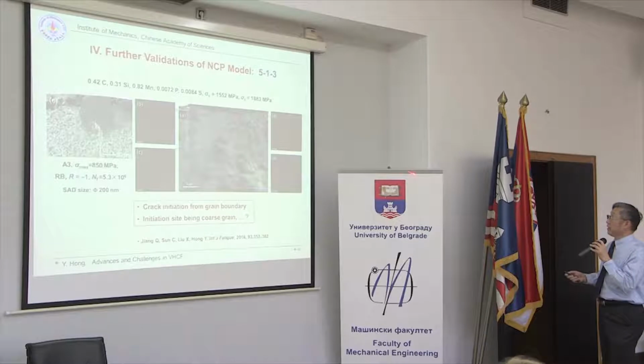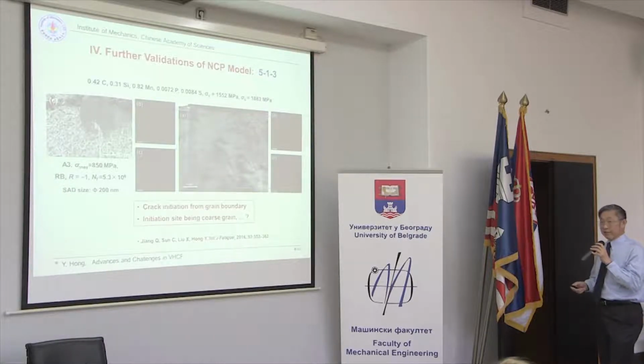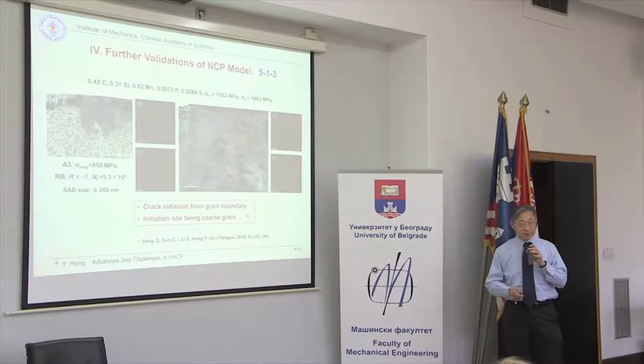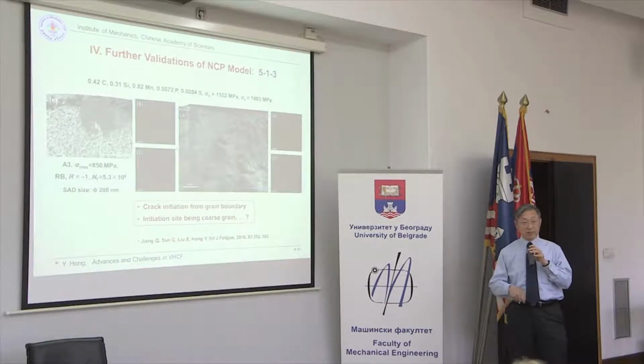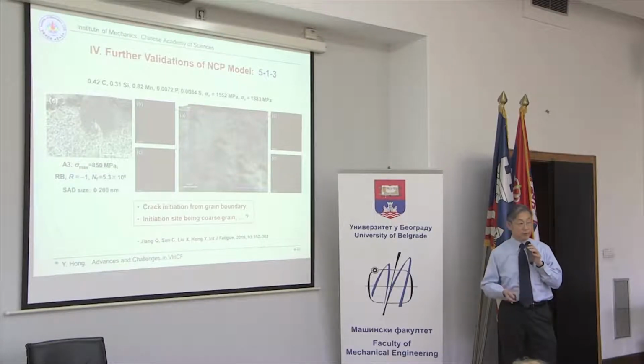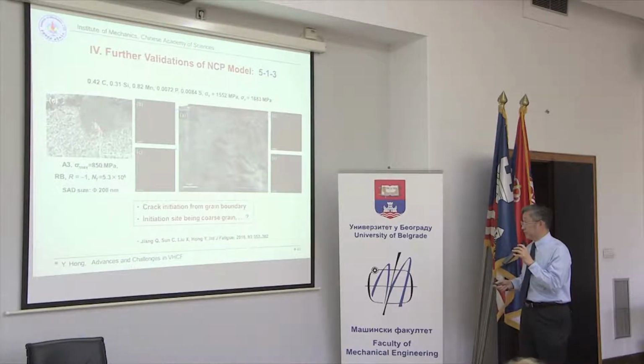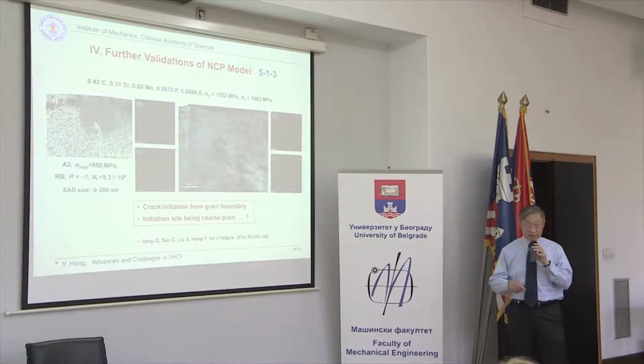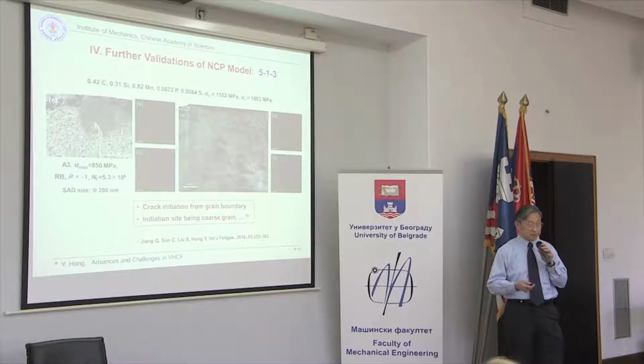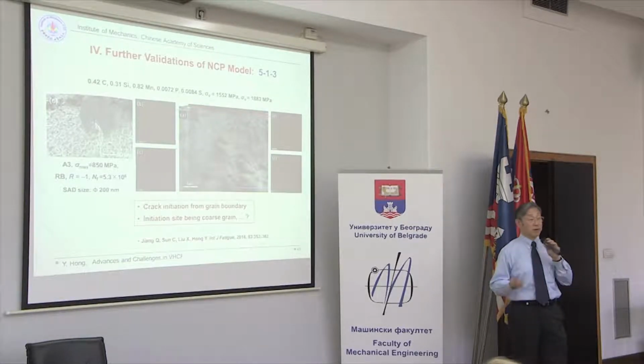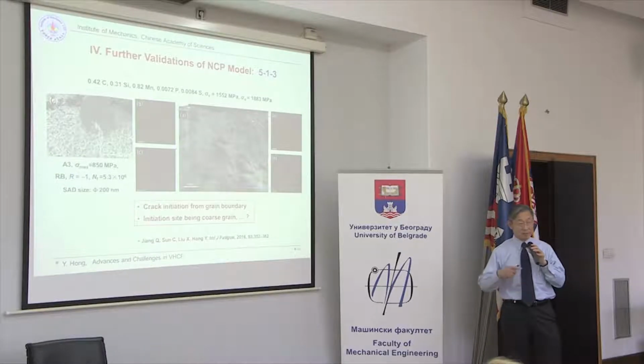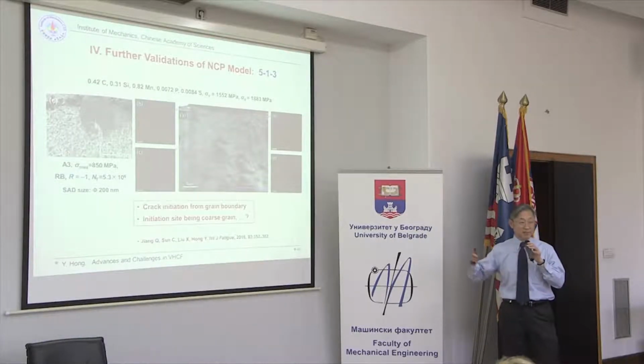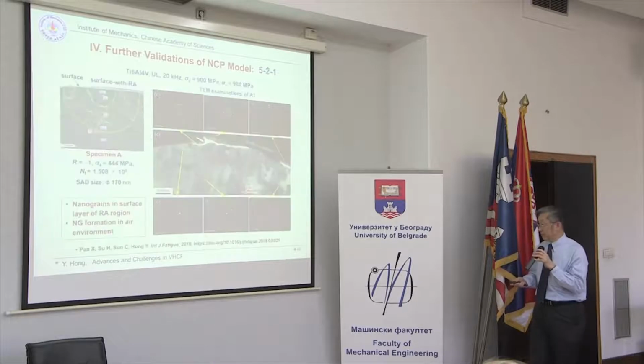And also, we observe that crack initiation, or internal crack initiation, may also form at a grain boundary. But for this type of process, the morphology underneath the fracture surface is not very clear evidence of grain refinement. We still have some questions, or we are still not quite clear about it. We also have some explanations for this, but we still need some further investigation for this phenomenon.